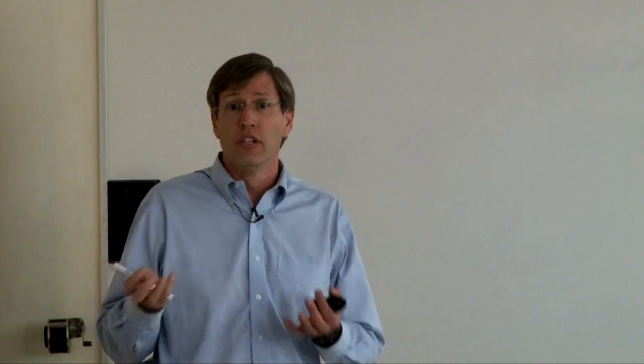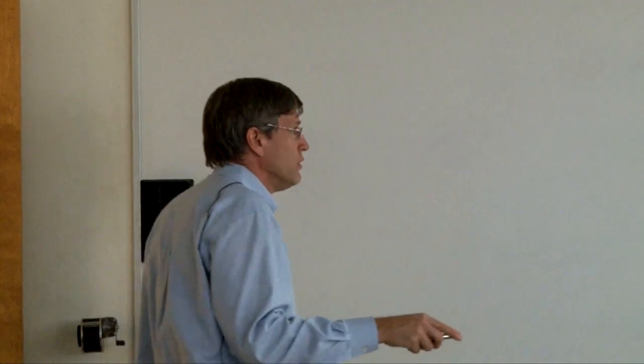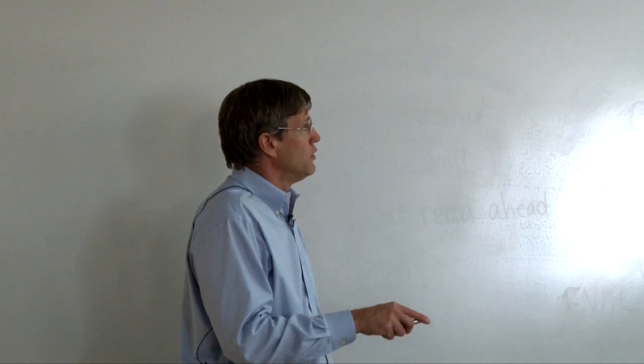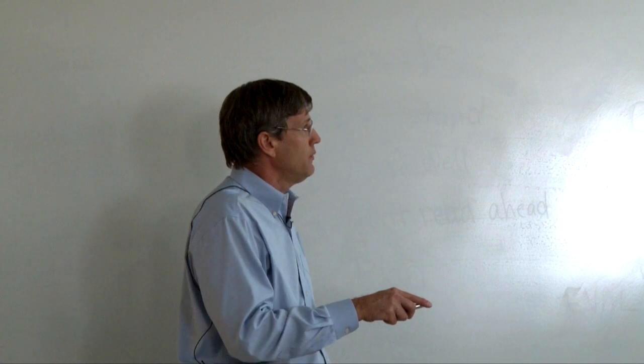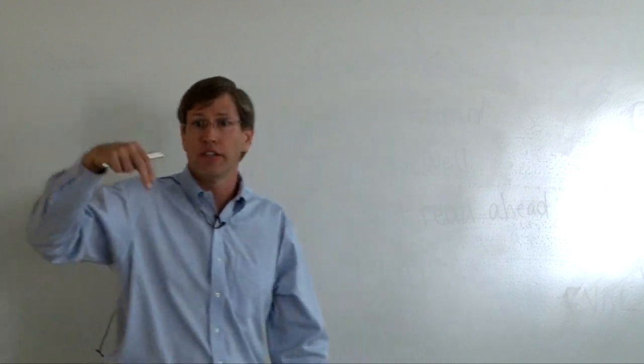In this case, we can see this sort of challenge if we look at the way that strong interaction is not going to make it easy for you to get migration through the lattice. You're going to be strongly interacting. If you're sitting there very strongly interacting, it's going to be hard to move that ion in the lattice. And so this is some calculations done by the Ceder group, just showing that, in this case, it's relatively easy to put a lithium ion through, but you get a significantly higher activation energy as you're trying to move through that lattice, okay?